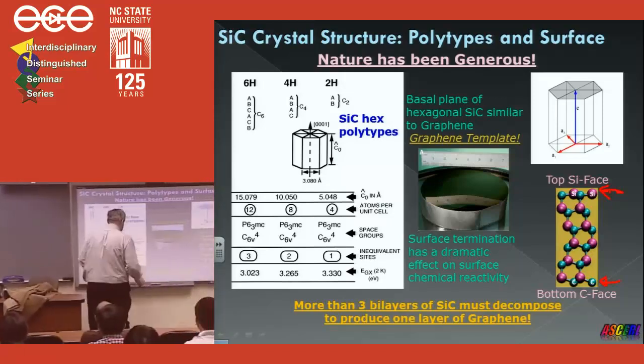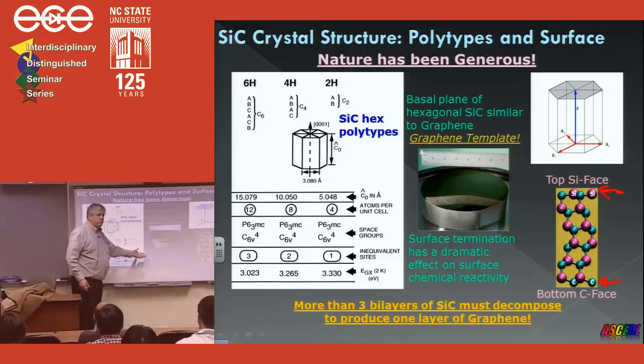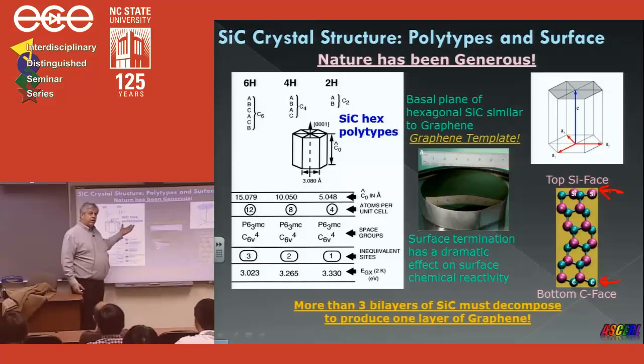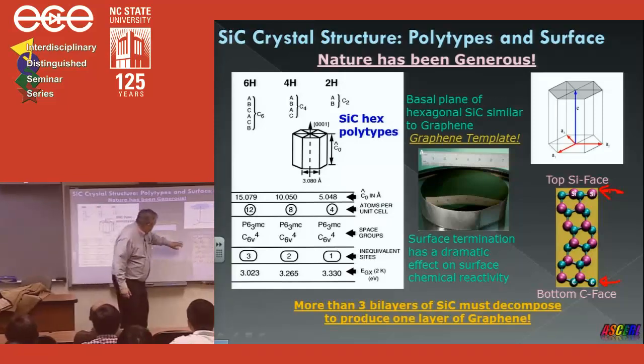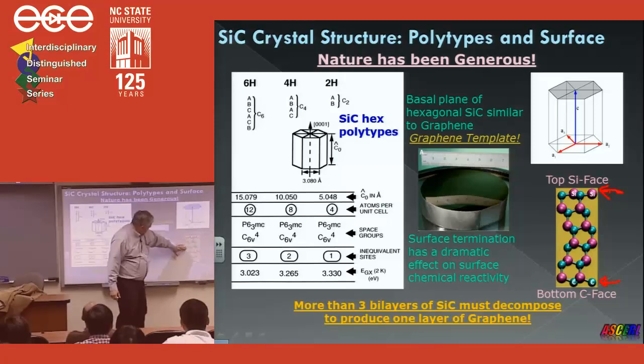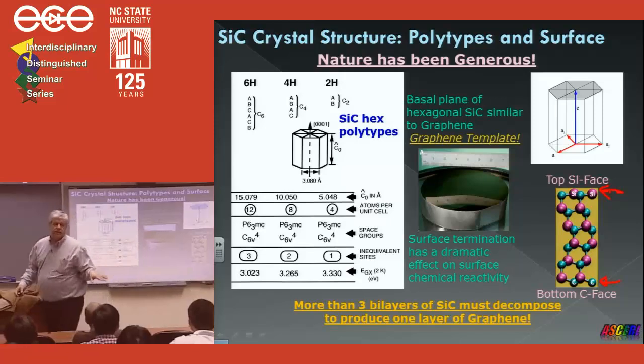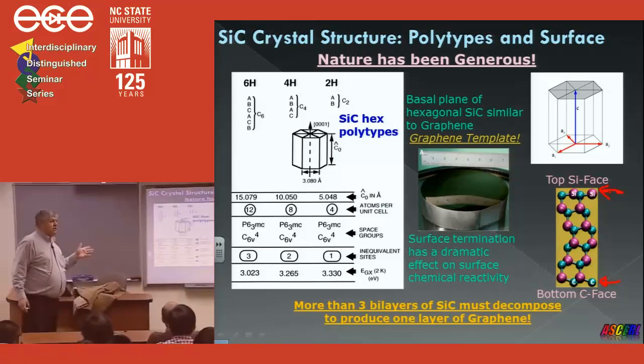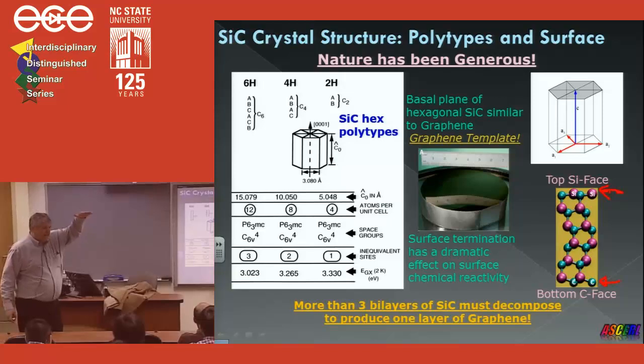Now, as I mentioned, the silicon carbide, it's a sublimation process. So I remove silicon atoms, and that allows the remaining carbon atoms, which have very low vapor pressure, so they don't disappear easily, to reconstruct into the graphene layer. But I need to remove 3 bilayers of silicon carbide. So I have to remove, here's a bilayer here, here's a bilayer and a bilayer. So I have to get rid of all 3 of these bilayers to get enough carbon atoms to make a single layer of graphene. And so that means the process of making graphene is below the surface that you started with. And so you might call it inverse epitaxy.